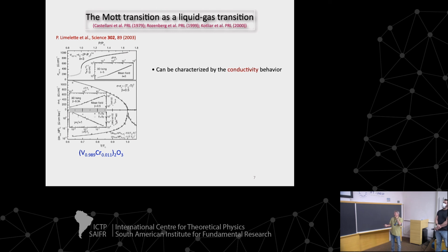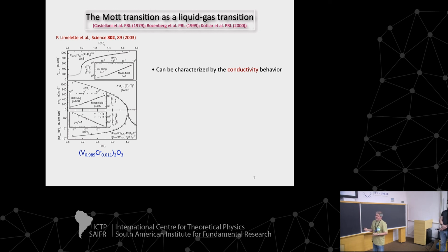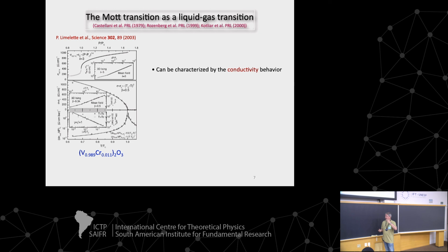The point is that this is an experimental result. It's a very small critical region. You can see here, this is the mean field exponent, beta equals 1/2. To get beta 0.34, you have to really zoom in on this thing here. It's like a superconductor. It's a very small critical region. Now, in our case, we cannot really do a good job of the critical region, because that would mean taking an infinite cluster. Sorry, I can't do that.